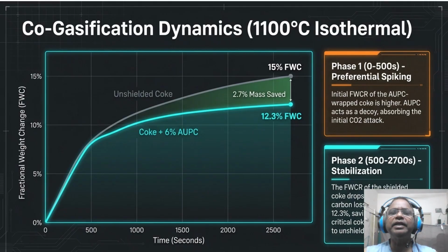So, understanding the co-gasification dynamics at the 1100 degree centigrade isotherm. Because feeling like it's working is not enough, we need to see the mass saved. Look at the chart. The gray line is unshielded coke. The blue line is our coke plus 6% AUPC. In phase 1, the first 500 seconds, the AUPC wrapped coke shows a higher initial fractional weight change.